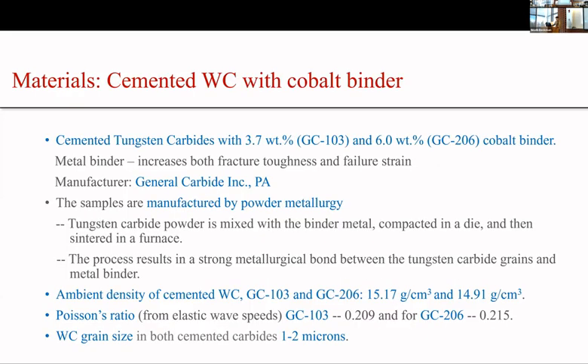The material being studied in our research is cemented tungsten carbide, containing 3.7 weight percent of cobalt binder and 6 weight percent cobalt binder. There are two grades of tungsten carbide. These are manufactured by powder metallurgy, where the tungsten carbide ceramic powder is mixed with the cobalt metal, then compacted in a die and sintered in a furnace. Before each experiment, the samples are characterized by ambient density and sound wave measurement.